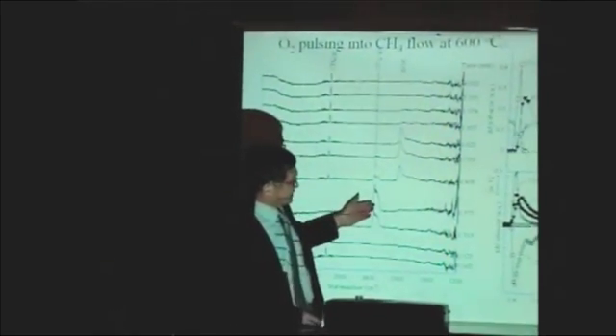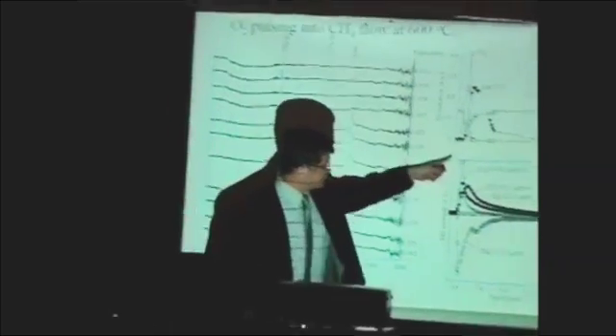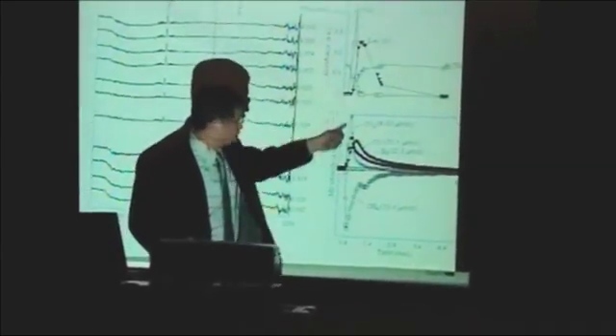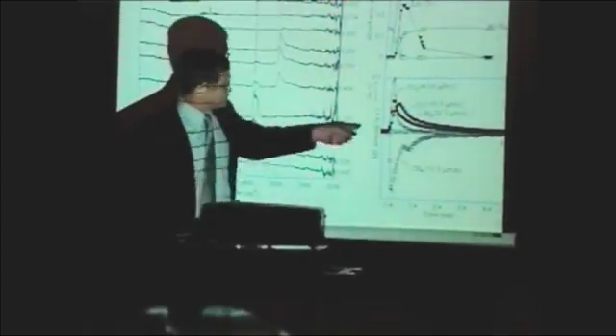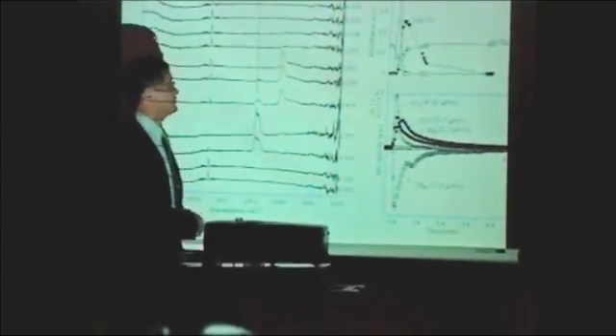Initially, when you pulse the oxygen in, there is too much oxygen in the reactor, so a huge amount of CO2 is produced. In order to do the partial oxidation, we need to control the amount of oxygen, and also control the amount of oxygen adsorbed on the catalyst surface, and keep the catalyst in the reduced state to produce the partial oxidation products. Recently, we also ran the partial oxidation of propylene.